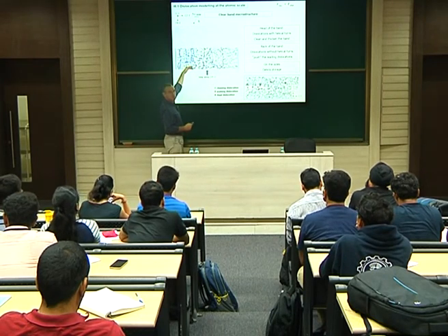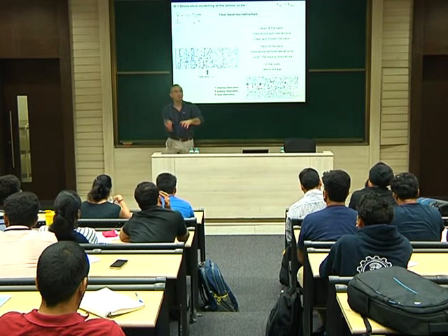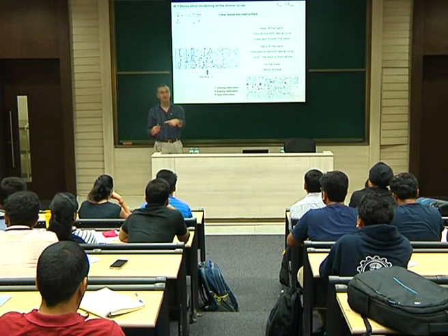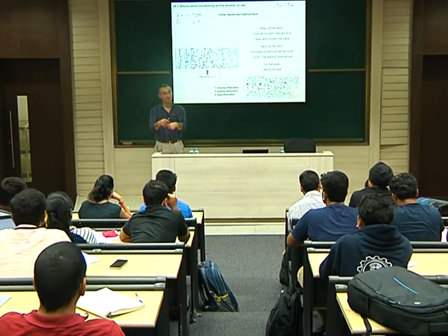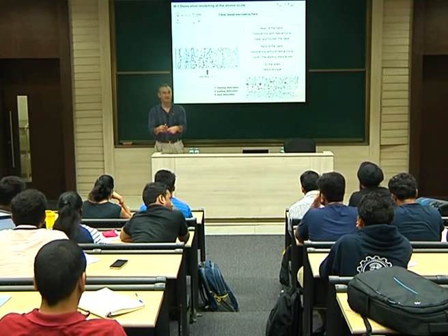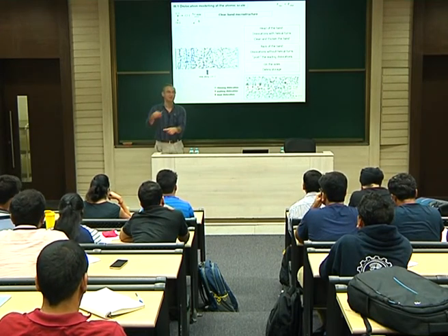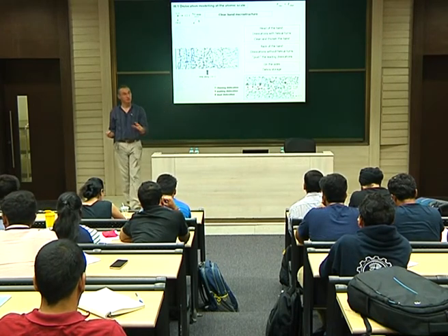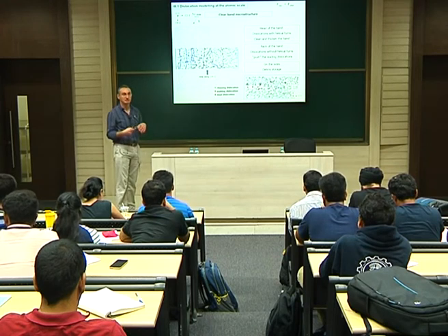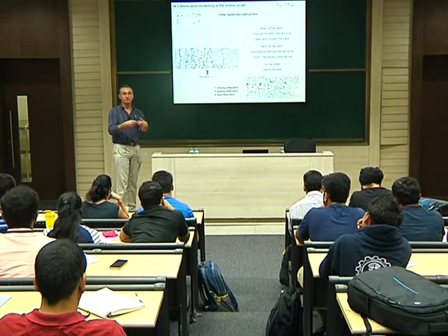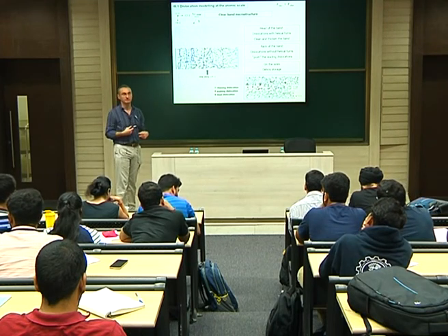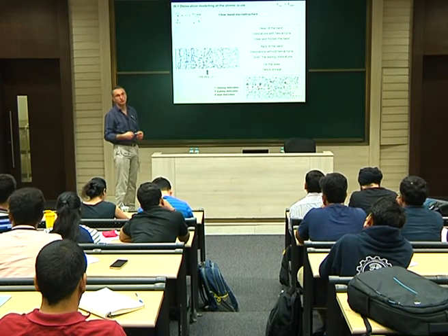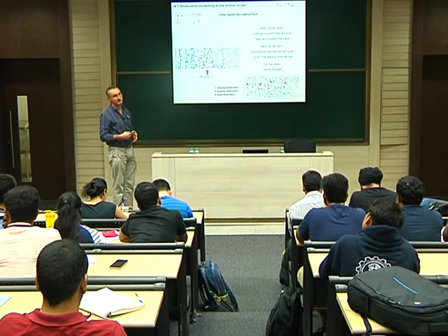So they are prismatic loops, because I don't have all the possibilities in my DD code to change the Burgers vector to react and create partials. So I already put them ready to react with the same Burgers vector. But they are sessile, and only if a screw comes will they be freed and can then reconnect. This is the local rule I introduced. I know this is artificial, I agree, but it is taken from the MD modeling. In MD, I saw that for any B I put, when it is unfaulted, the new B will be that of the incoming dislocation. So here I already put that of the incoming dislocation. It is artificially introduced, but this mimics what we found with MD.